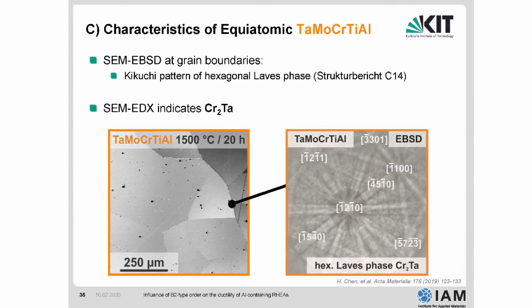We have done this, I can skip this. Because of the tantalum and the chromium inside there, we again get a hexagonal Laves phase. This is chromium-tantalum in this case, and you can see it here as nice little bright spots on the grain boundaries. Of course, you can imagine that this brittle phase on a grain boundary is not good for structural materials, because if you want to plastically deform it, it would fail. And I will show you an example for that in a minute.